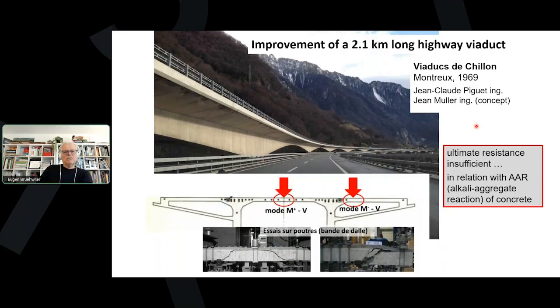Very nice design, very innovative, and without going into detail, after some years of use, we had to state that in addition to the usual rebar corrosion problem, we have alkali aggregate reaction in the concrete, which of course is progressing once there is water going inside the concrete. So the problem was actually that the slab that they designed at that time in the 1960s is rather thin, and we had to design an intervention.